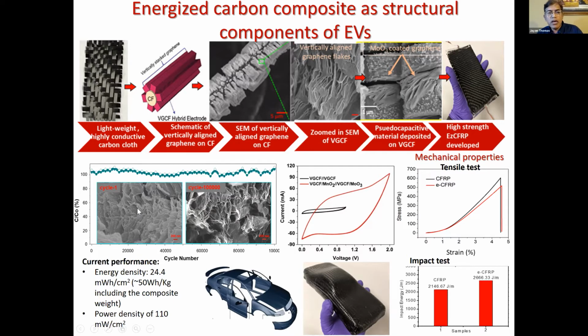But if you look here, why it is so important: you can see that this graphene on these carbon fibers can go to whatever number of cycles. This is the number of cycles, okay, you can see the number of cycles there. It gives you a very stable performance for quite a long time, for 100,000 cycles.